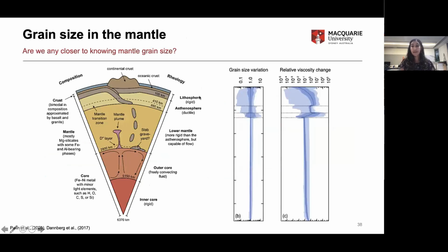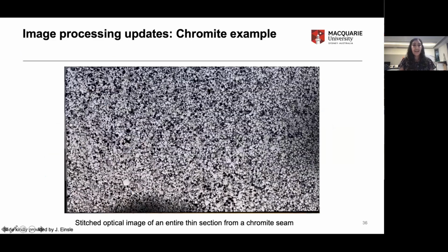And Dannberg and co-authors were also very aware of this. And so when we start to look at the grain size variation, they showed that actually the relative change in viscosity can be over 5 orders of magnitude if we're really trying to use the most up-to-date grain growth kinetics. So whilst we may not be any closer to knowing the exact grain size of the mantle, we can at least measure grains better and more consistently. And this work's not finished yet. We are working on some image processing updates, and we're really trying to build a better mechanism so that it's more available to people not using SEM images.